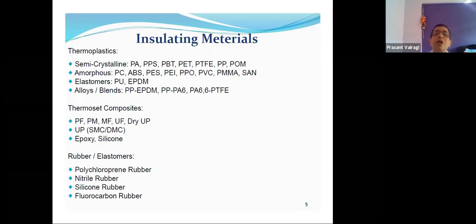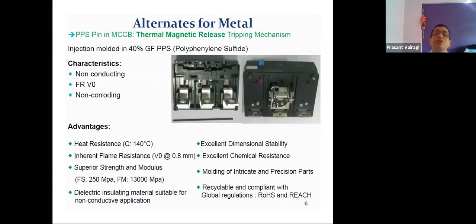But then during the arcing, in the MCCB, which is not taking place in this release, because of the metal, the arcing was getting attracted towards this metal pin. This was of mild steel, and in order to prevent that, earlier the Teflon coating was done. So why do all those things? We have converted that into 40% glass-filled PPS material, which is inherently flame retardant and non-corroding and obviously non-conducting.